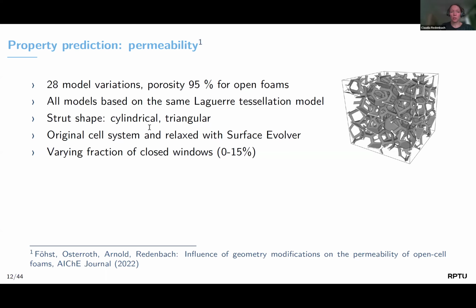What we did vary was the strut cross-section shape. So we had circular cross-section to get cylindrical struts, and then these triangular ones as you see them here. We used the original cell system and a cell system relaxed with Brakke's Surface Evolver. The idea here is that in some studies we observed that Laguerre tessellations, even though being already more regular than some of the Voronoi examples that we have seen, tend to have too many small edges, and a surface evolver mimics steps of foam evolution, and it makes the cell shapes even more regular. And we saw that this makes them also closer to some foams that you really observe in practice. So in some cases, we found this relaxation to help to look more like the observed structures.